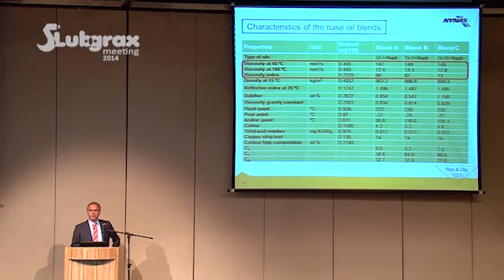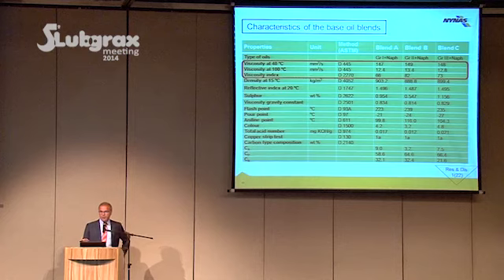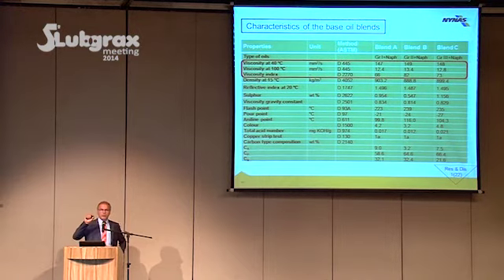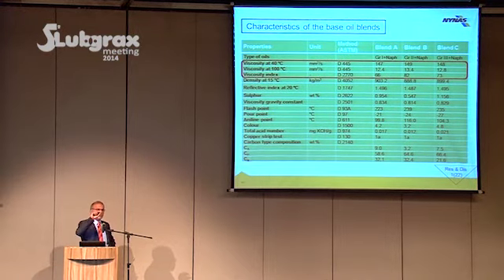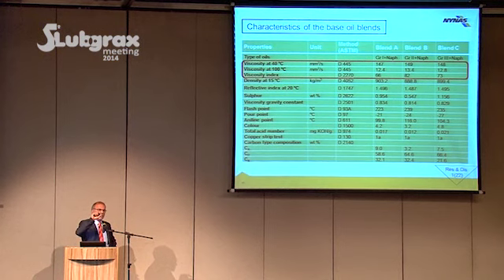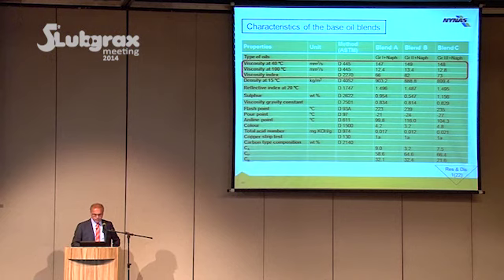We had a presentation from Lubrizol, where we saw the use of functionalized polymer in order to increase the adhesivity of the product. By using a small amount of polymer, not only do you improve the adhesivity of the product, you improve the film thickness as well as the viscosity index of the oil. On top of that, you have the contribution from the soap. Soap contributes to separating surfaces. So indeed, the viscosity index in greases should be discussed differently from other applications, for instance, hydraulics.